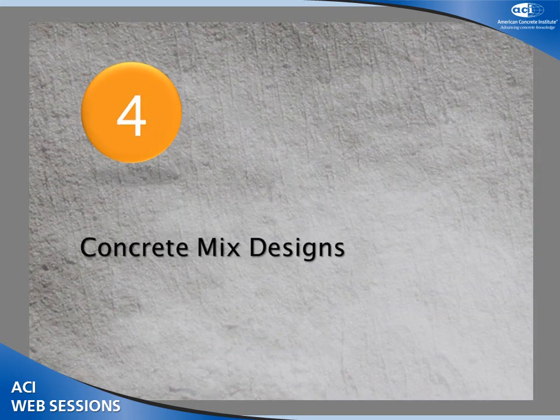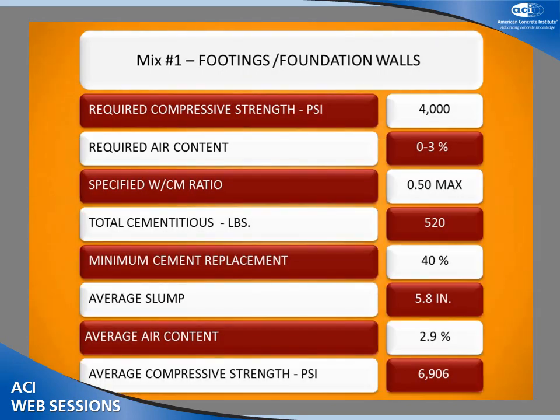Here's our mixed designs, kind of related to our specifications. See here that for a 4,000-pound footing and foundation wall, we had a little higher water cement ratio. That's no problem. You can even go a little bit higher. I want to focus on this, and that's throughout all of our specs. We take a two-pronged approach to green concrete, and that is, number one, limit the total cementitious content. We've been over-cementing our mixes for decades, and we've got great results with keeping many of our mixes down at 520 or even below that. So we limit the total cementitious, and then we replace 40%.